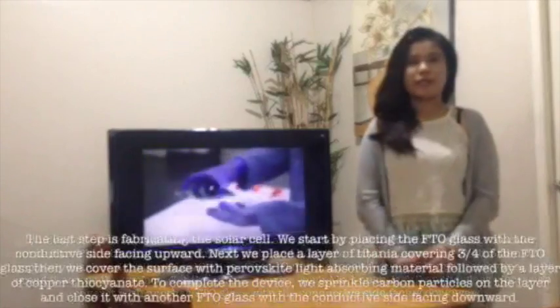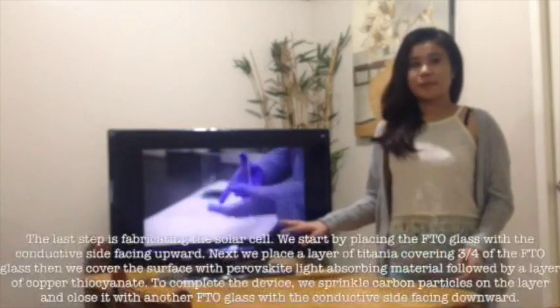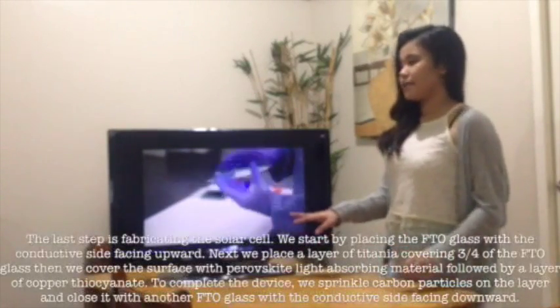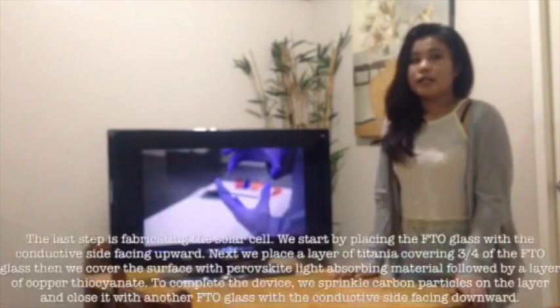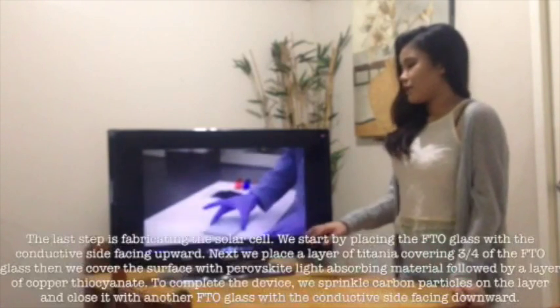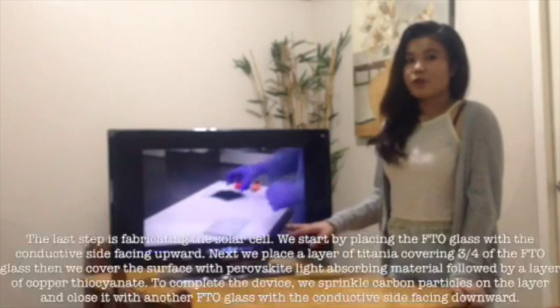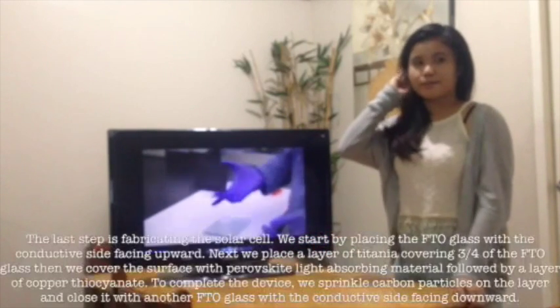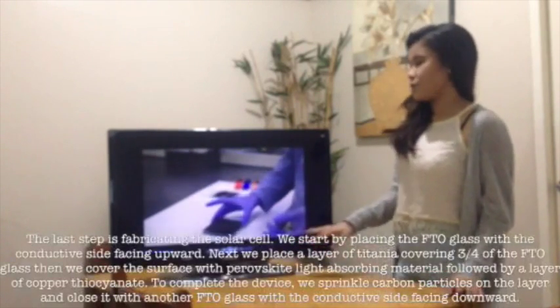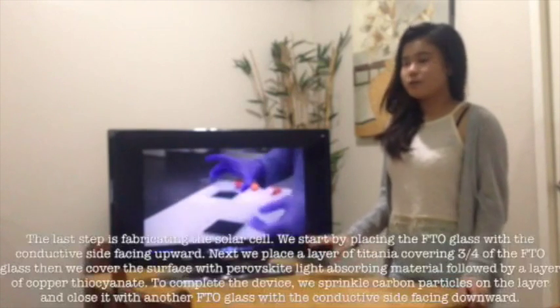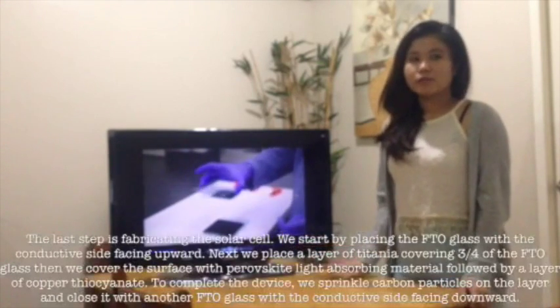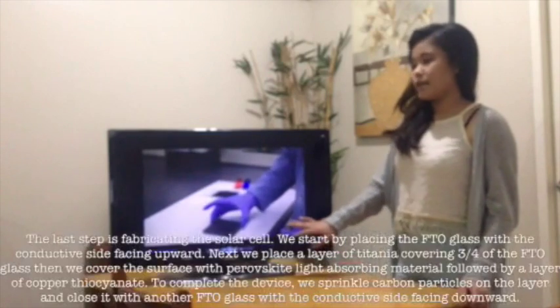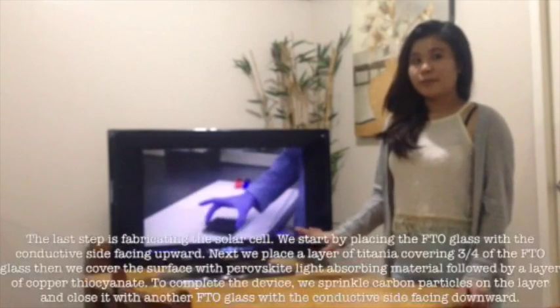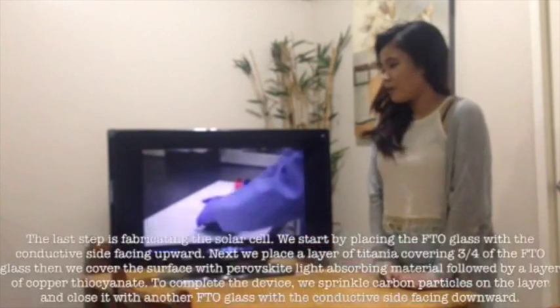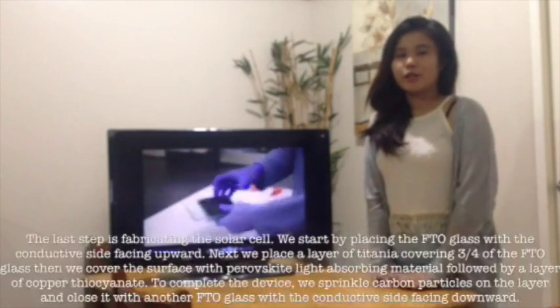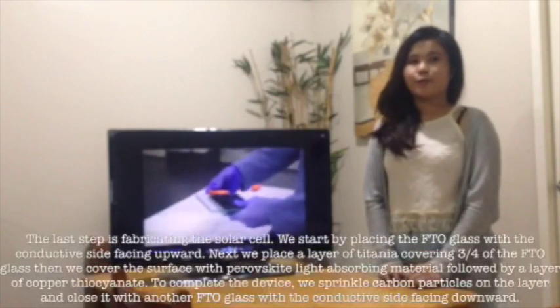The last step is fabricating the solar cell. Start by placing the FTO glass with the conductive side upward. Next, we place a layer of titania covering 3/4 of the FTO glass. Then we cover the surface with a perovskite light-absorbing material. Next, followed by a layer of copper thiocyanate. To complete the device, we sprinkle carbon particles on the layer and close it with another FTO glass with the conductive side facing down.